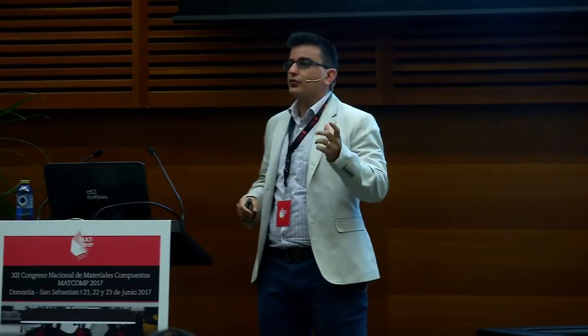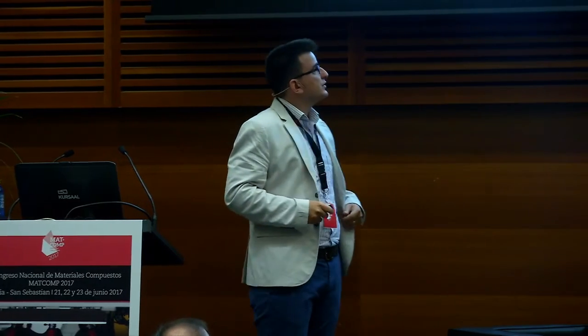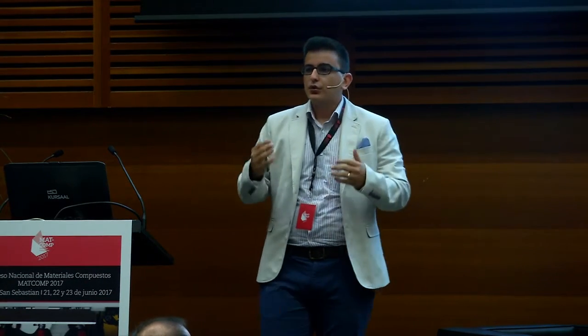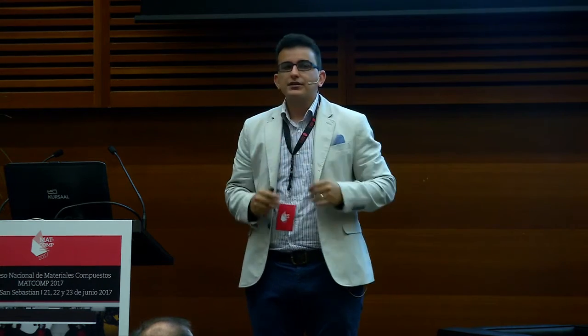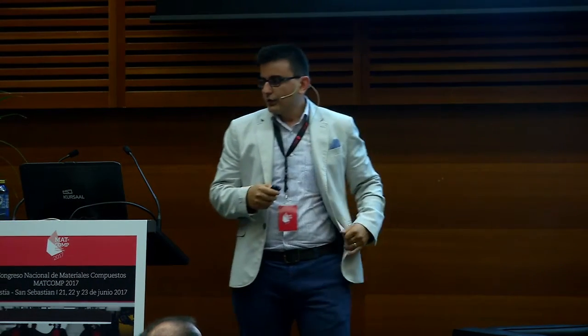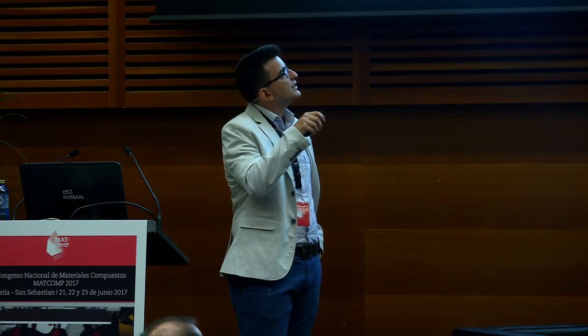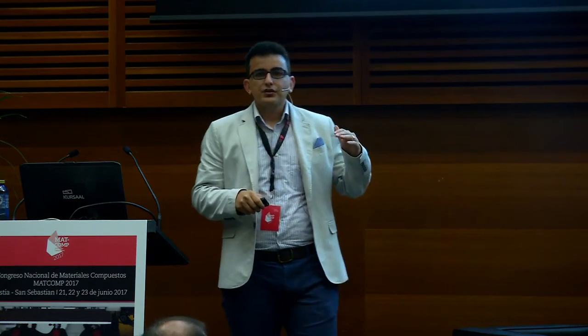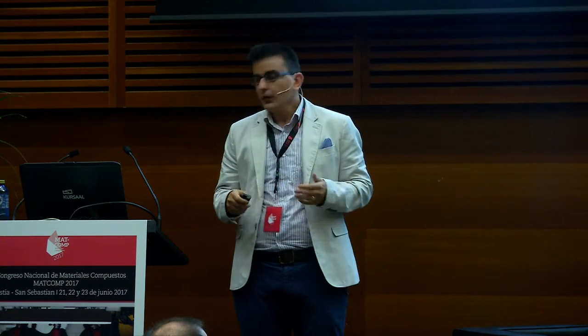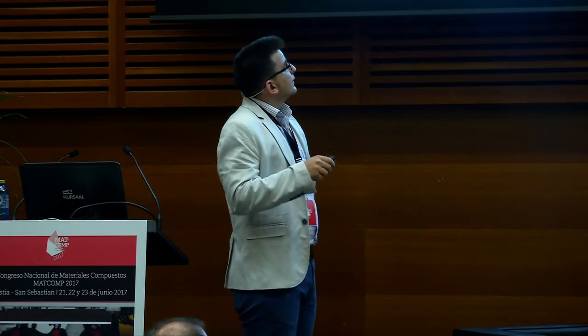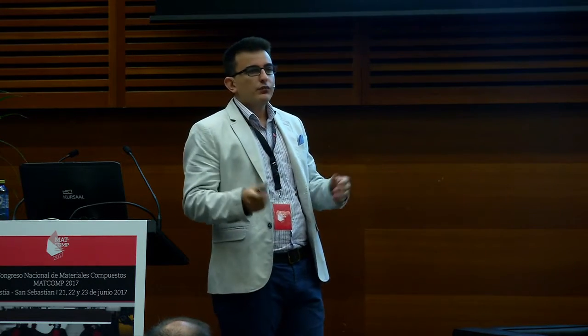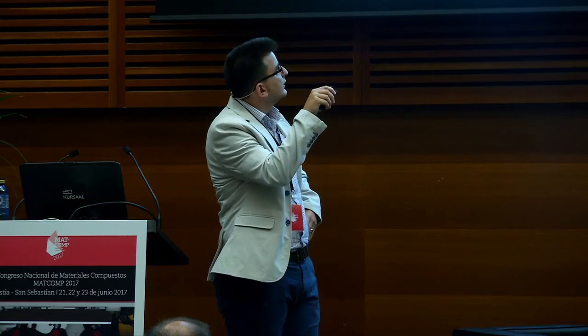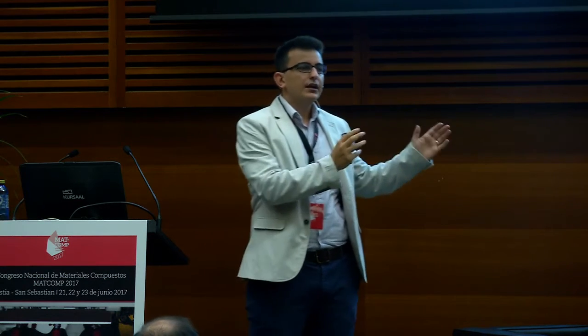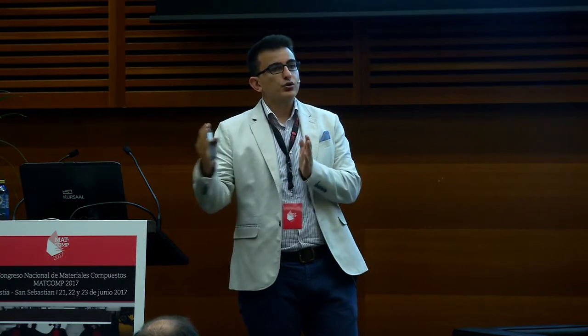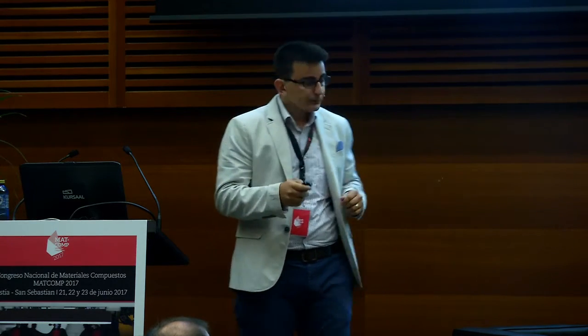Here we have an example of an industrially pultruded angle profile, which is used in the construction industry. And here the dimensional stability of the angle between the legs is very important. And this profile consists of a unidirectional layer inside and outside mat layer, continuous filament mat, CFM. And the material was glass polyester. Using the developed process modeling framework, actually we can predict the evolution of springback inside the die mold as well as in the post-die region during solid state cooling.